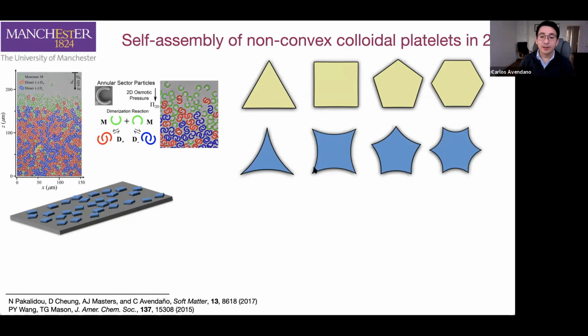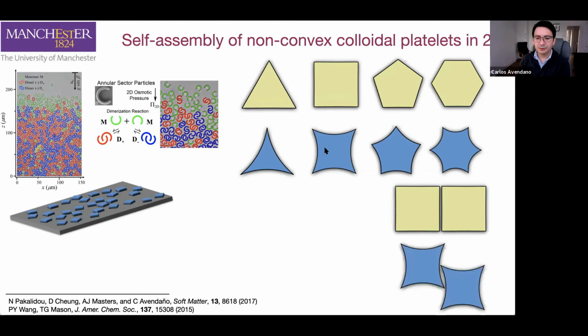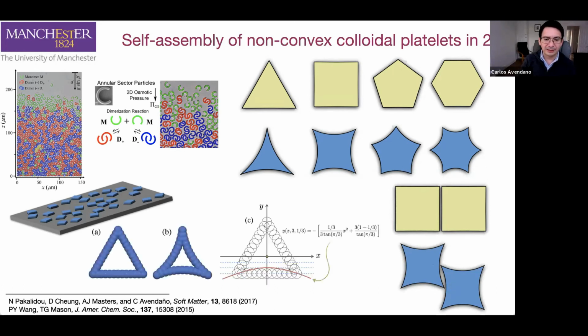the particles are not going to be able to interact in the same way. So imagine the case of a square particle. When they come together, the 2 edges will try to align at high densities. But for the non-convex counterpart, that cannot take place. And what will happen is that the particles, rather than being aligned, will start shifting by a certain distance, because that will maximize the packing between these 2 structures. So we decided to analyze that type of systems.